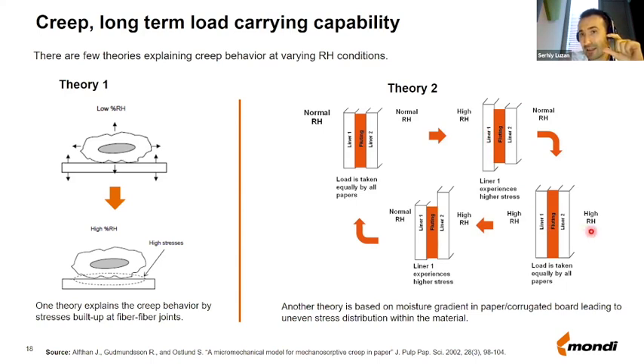Then, as the humidity is stabilizing all the way across the board, all papers again have, let's say, the same length. But then when you lower the humidity outside, again the paper outside starts to shrink first, while inside the box the humidity is still high and the paper is still longer. And then liner 2 is taking all the load, and therefore it is damaged more than liner 1. As you go in cycles, step by step, you introduce damage to liner 1, liner 2, liner 1, liner 2, and after some cycles, you get a packaging which is collapsing.